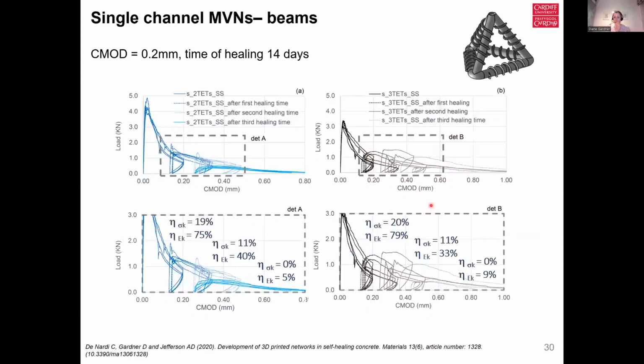We also have instances of repeated healing with these cycles of 2 and 3 minivascular networks. At first sight, an increasing number of minivascular networks does not appear to have a positive effect on the flexural strength after healing. This suggests that not all minivascular networks were intersected by the crack, and thus not all of the sodium silicate stored inside was able to be released during the healing process. Nevertheless, when considering the fracture energy, the recovery index underlines a positive influence of a greater number of minivascular networks. After the third damage-healing cycle, the concrete minivascular network system appears to have consumed the reservoir of healing agent within the TETs themselves, within these minivascular networks. The strength recovery index towards the end is negligible.